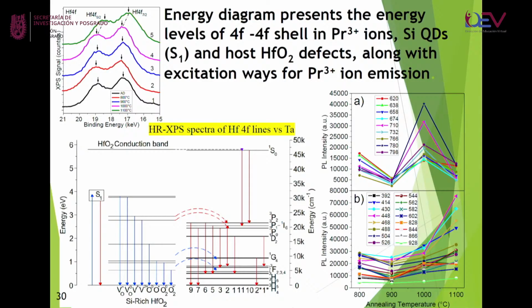And we also show here how the intensity of the low energy band detected in the praseodymium atom changes with oxygen, and how vacancies appear and the low energy intensity decreases, because the level of oxygen is low and the level of vacancies is higher. Due to this, when vacancies appear, the higher energy band appears in the spectra of praseodymium atoms.